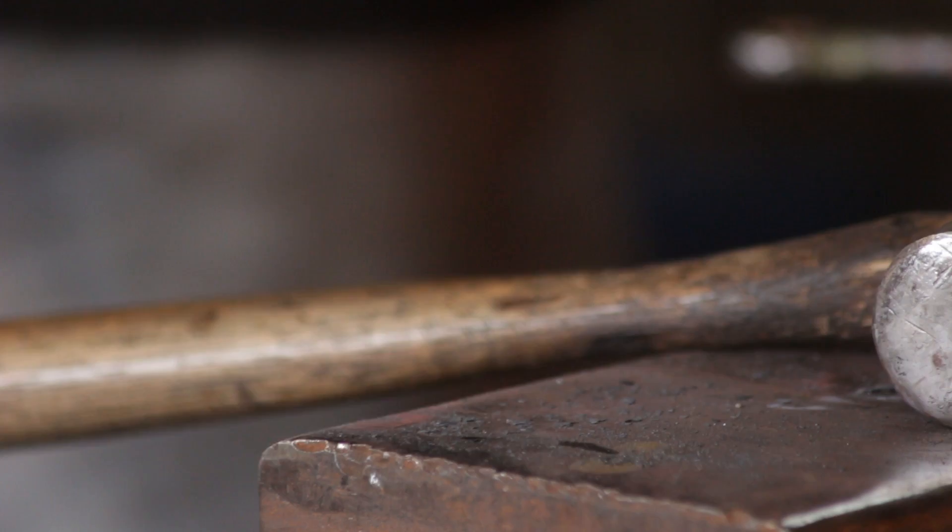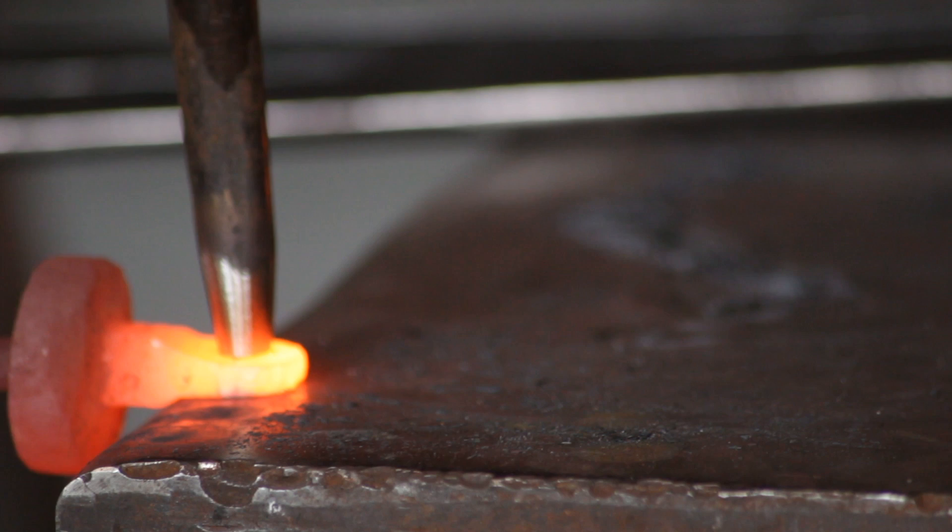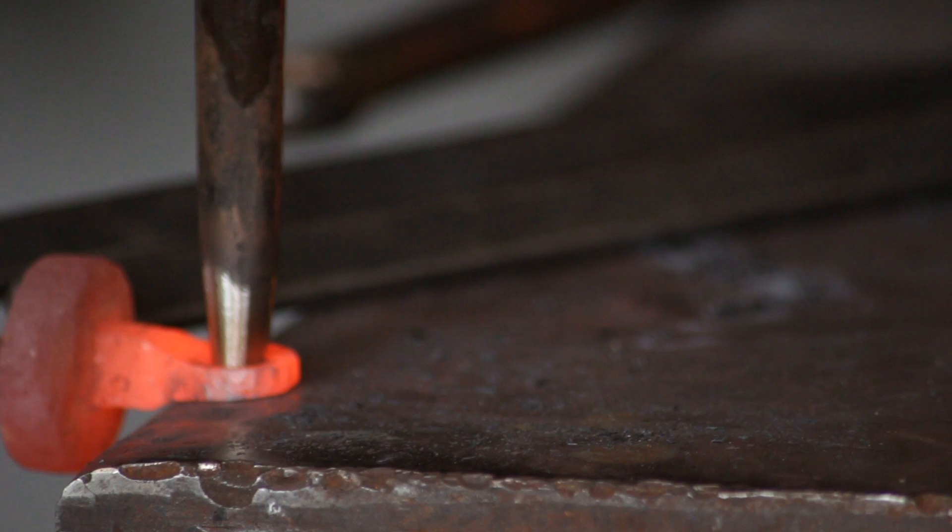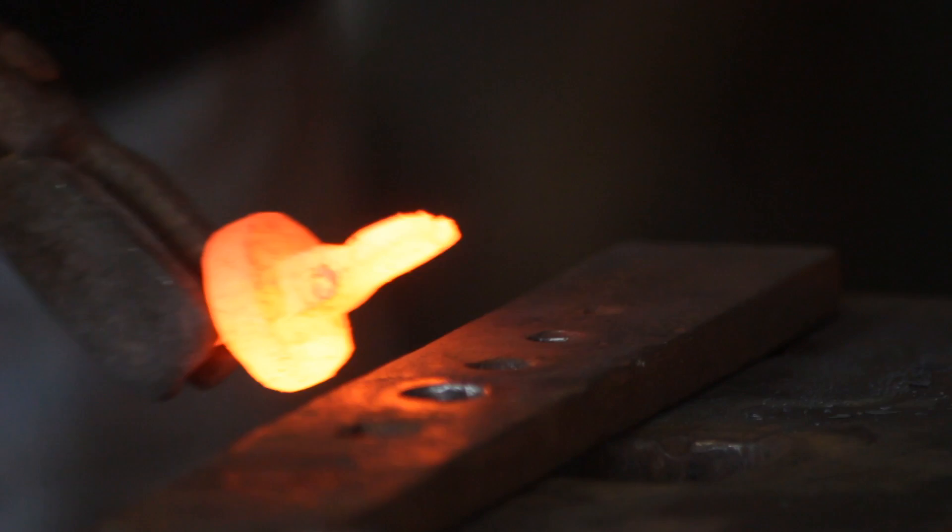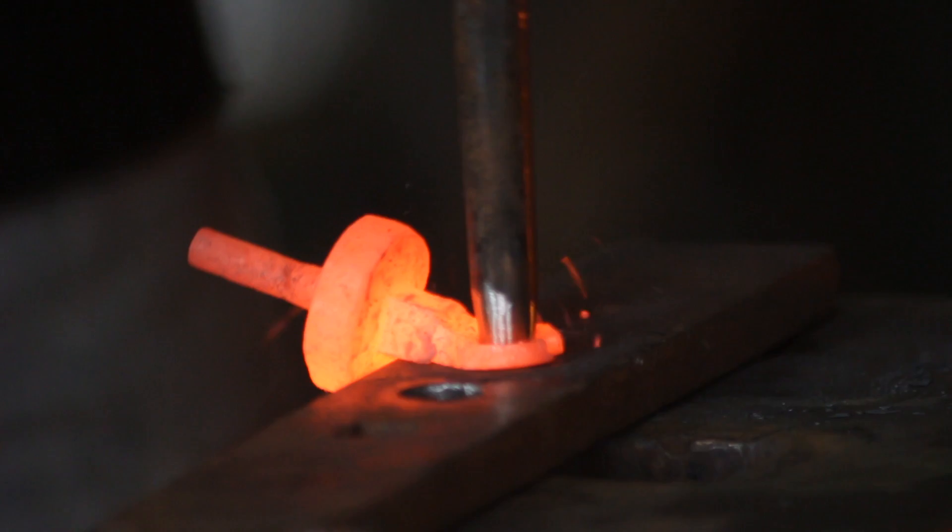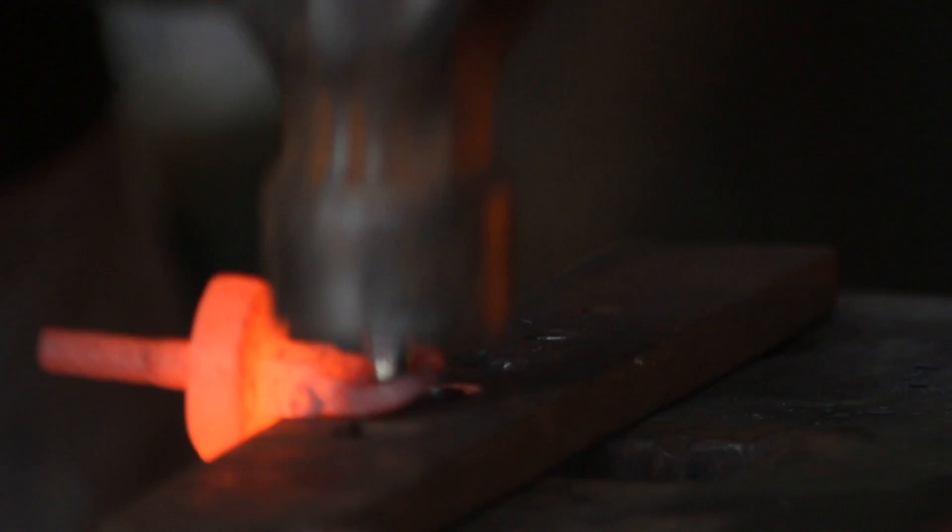And then I attempted to hot punch it. So this is standard punching. Punch through one side. Shear the slug. And at that stage you could see the material actually splitting. So I blithely continued as before and used my bolster plate to drive out the slug most of the way anyway. However as you can see it did split. Now I did suspect that this would happen. And it's not really that much of an issue.